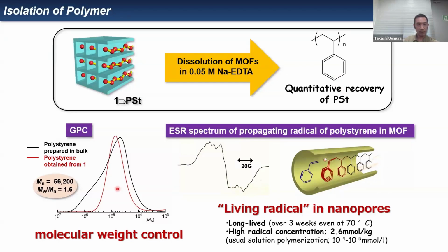Then we checked the GPC and found that yes, this is really a polymer with high molecular weight, and also with a very narrow molecular weight distribution. So next, we checked the ESR and found that the propagating radical was very long-lived, over 3 weeks, even at 70 degrees C. And the radical concentration was extremely high compared to the usual solution polymerization system. So this is because the propagating radical was protected in the channels, and a kind of living radical polymerization proceeded in the channels. That's why we could attain the narrow molecular weight distribution shown here.